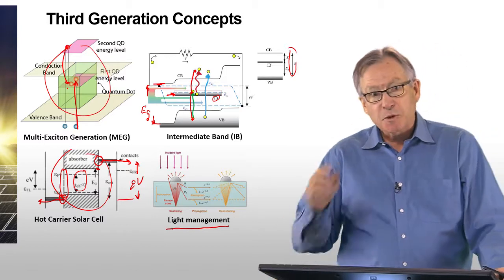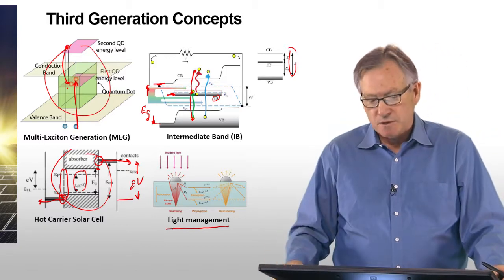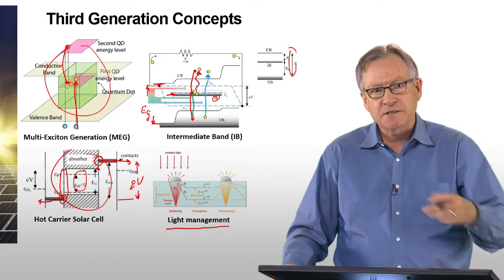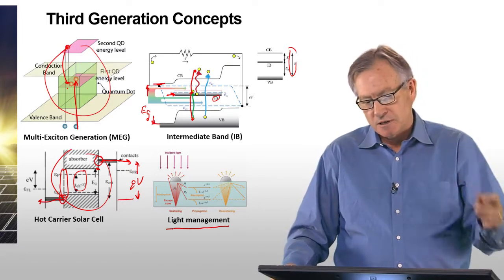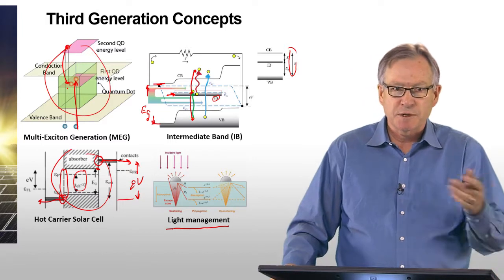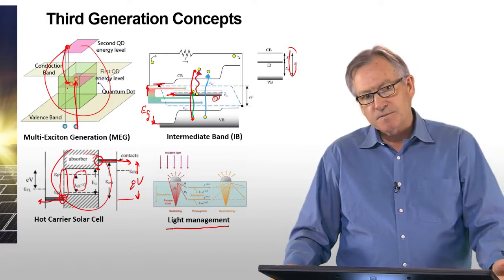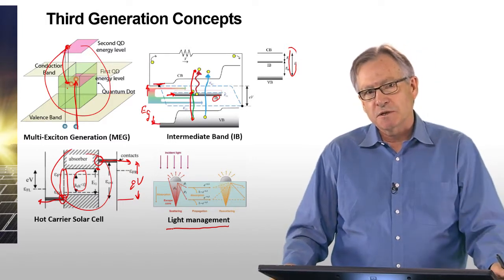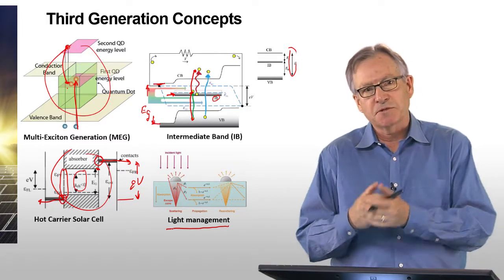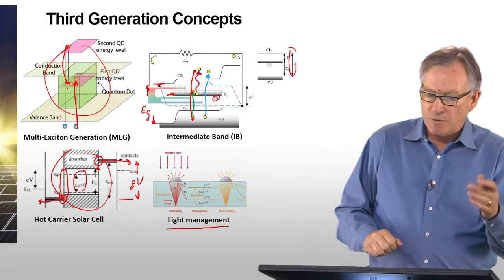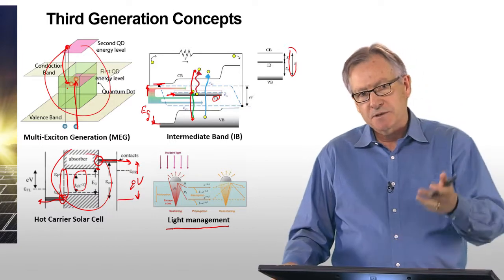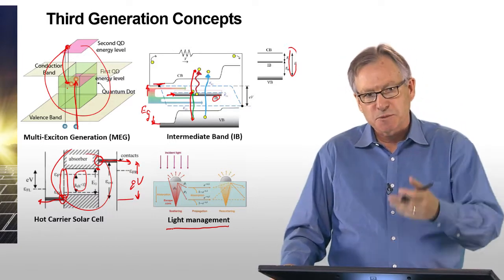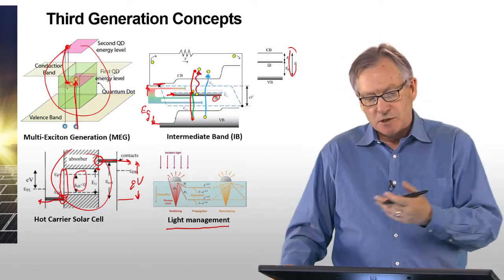Another important issue is that of what we call light management. And that is, how do we absorb more of the light that's coming in and not lose it, for example, due to transparency. This is particularly important for materials like silicon, because silicon has a relatively low absorption, and therefore a lot of the light, particularly the long wavelength light, is not absorbed in the silicon and is lost.